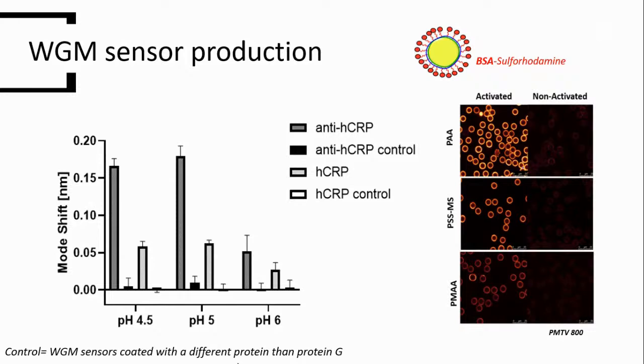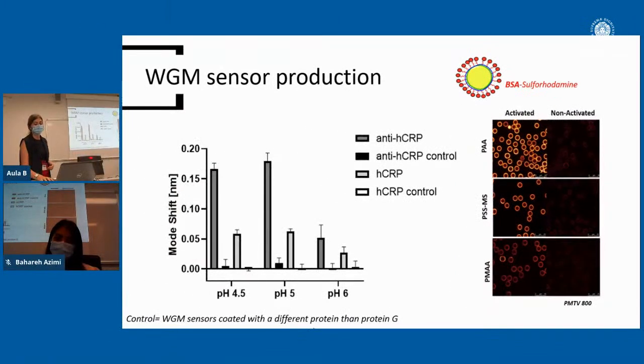And also, we coupled fluorescent labeled protein, BSA in this case, just to see how was the distribution of the protein on the surface of the particle, because thousands of sensors are produced in one batch. So it's important that the distribution of the protein is uniform in between the different particles to have robust statistics. And as you can see in the images, the distribution is really uniform. And again, the polyacrylic acid gave out the highest protein coupling on the surface.